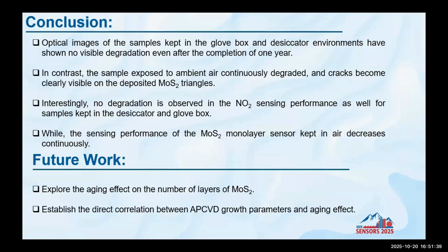So this is the conclusion of this presentation. I have grown APCVD-grown monolayer MoS2 and kept it in different environments: glove box, desiccator, and lab environment. We found that the samples kept in the open environment show large degradation compared to the samples kept in the desiccator and glove box. In future work, I am trying to explore the aging effect on the number of layers of MoS2. Is there any effect if we grow bilayer or tri-layer, which may be more stable than monolayer? I am also exploring a correlation to improve the stability of CVD-grown monolayers by controlling the growth parameters.